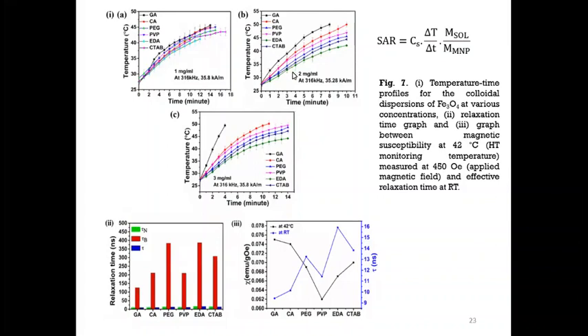Of course, it depends on the concentrations too, because the heat generation depends on the mass of the solution and the mass of the magnetic nanoparticles we are using. So this is 1 mg per ml, this is 2 mg per ml, this is 3 mg per ml, and this is the field which we have generated, 35.8 kilo amps per meter. This is the H, and this is the frequency of the applied field at which we are conducting the hyperthermia. We can see that around 45 degrees can be generated in less than 5 to 6 minutes, not in all the materials, but according to the magnetic parameters the magnetic heat generation is there. Less than around 10 minutes, you can generate it.